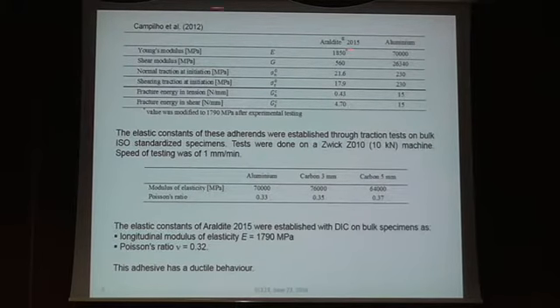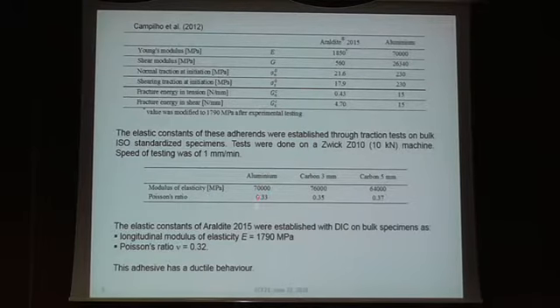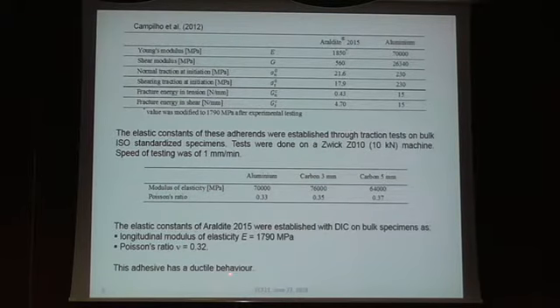As I was mentioning, the mechanical properties of Araldite and aluminum were taken from the literature. We also did experimental testing to verify Young's modulus and Poisson's ratio, conducting tests on a traction machine at a speed of 1 millimeter per minute. We established on bulk specimens the Araldite longitudinal modulus, and this value from the literature was slightly corrected by our own tests. For the carbon adherends of 3 and 5 millimeter thickness, we also performed our own tests and obtained the elastic constants.